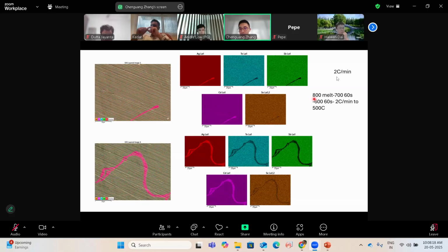The only manual intervention here is that we need to control the melting status. We control the 800 Celsius, and then we see the material melt. So we skip this program, and then we make the others the same, like 600 Celsius for 60 seconds and 700 for 60 seconds. They are almost the same. It's controlled by the program itself.